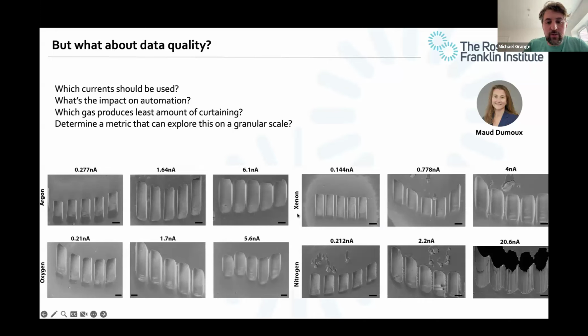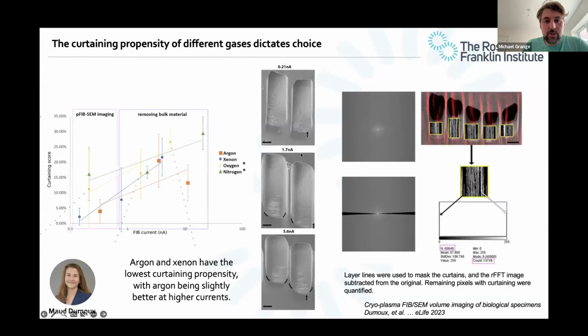So you can see here a panel of different images acquired where you've basically milled a ramp, and then we've imaged the ramp and just tried to determine the curtaining. And in the bottom right, you can see nitrogen at high currents has a really large amount of curtaining. And so what Maud did was to essentially try and work out a score to assess this.